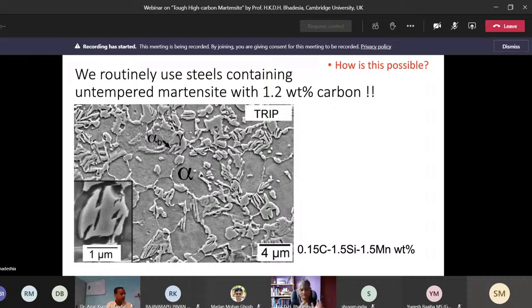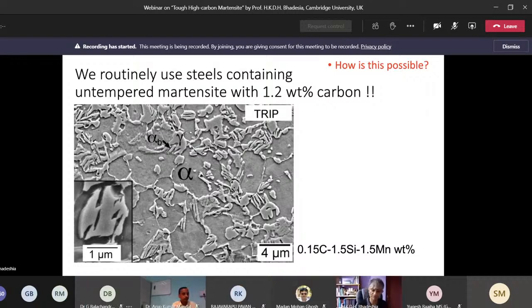How can we cope with a steel containing untempered martensite with 1.2 weight % carbon? Well, the first thing to note is that this is a scale of 4 micrometers. So these regions are actually of the order of 1 micrometer, and therefore we are limiting the length of the martensite plates, all right? And when it comes to welding, the average composition is fine. You will not produce brittle martensite in the heat affected zone, because that martensite will simply contain 0.15 weight % carbon after that region has been fully austenitized. So obviously this material does not have a high strength because it's not completely martensitic, but nevertheless